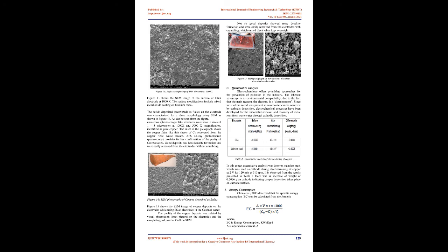Figure 9 shows the diffractogram of the deposited copper obtained at 2V, 120 minutes at 510 rpm, which had the maximum copper recovery percentage of 32.62% in monopolar batch study. It shows very broad and shallow diffraction peaks with one high diffraction peak. Bragg reflections possessing very broad humps and low intensity indicate that the analyzed phase possesses short range order, i.e., amorphous or very poor crystalline in nature, and the high peaks indicate high crystalline nature. The deposited copper showed both crystalline phase as Cu and poorly crystalline phase as Cu2O.